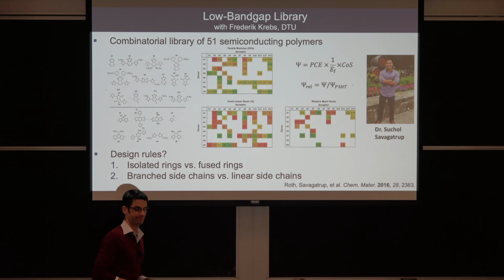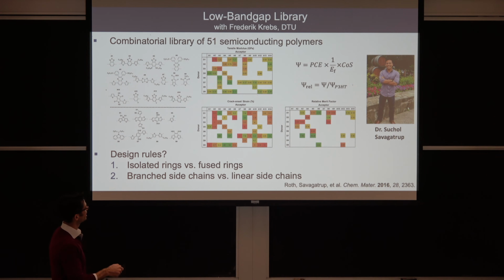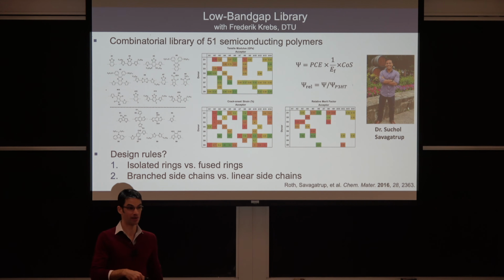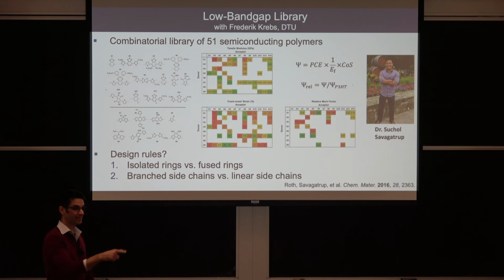Yep. So the merit factor chart, I noticed, doesn't have the same number of blocks as the other two charts. Yep. Okay, so for the merit factor chart, we had to be able to measure the modulus and the crack onset strain and a solar cell. So we only included data here for the materials that we could measure all three parameters. Okay. Yep. So it looked like A5D7 block was the best? A5D7 was the hero of this experiment.